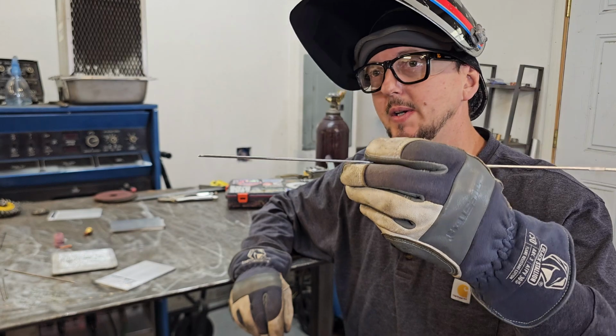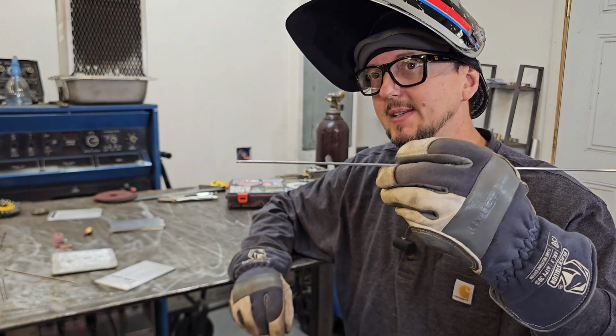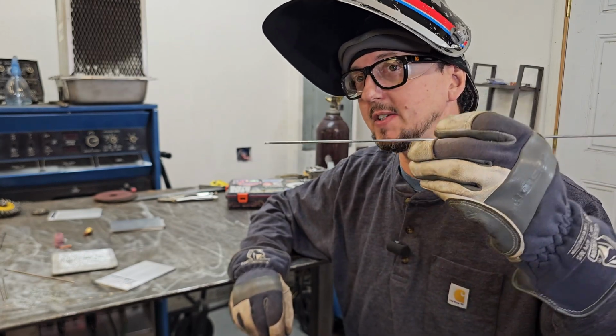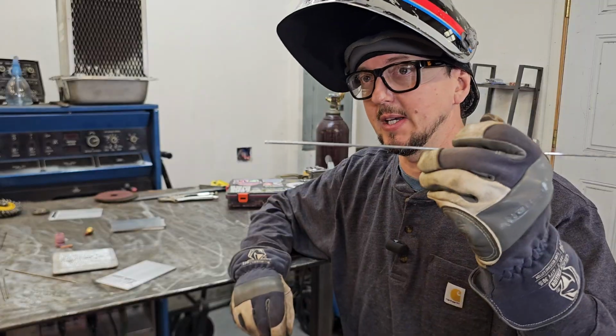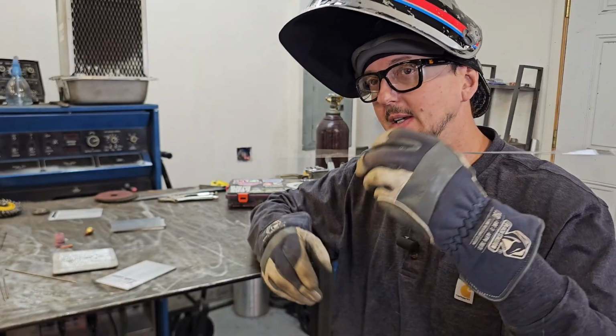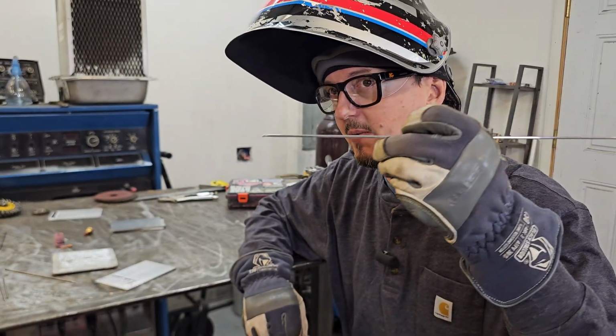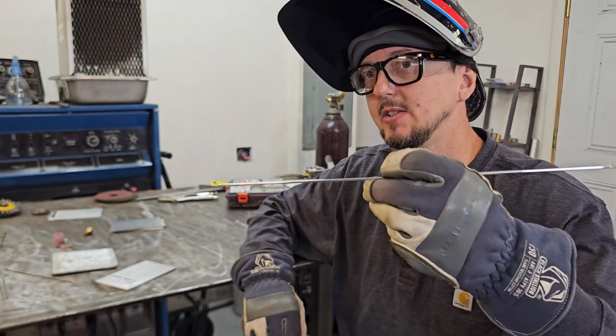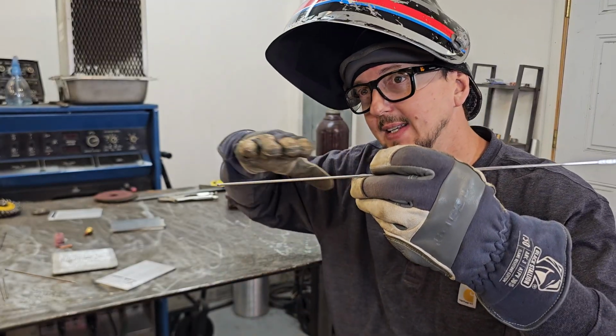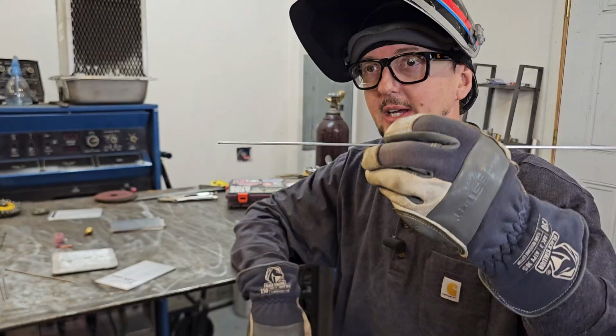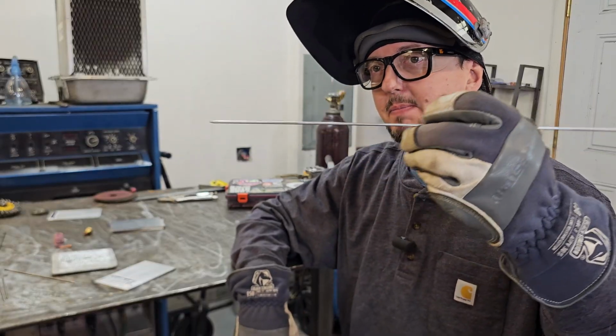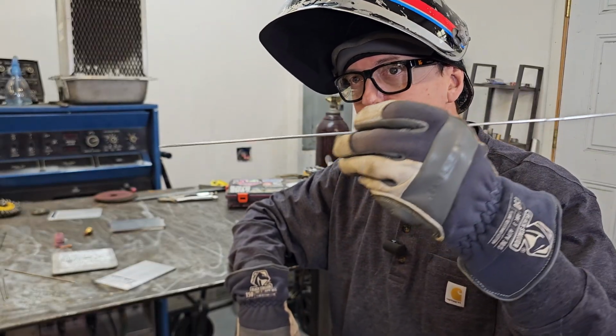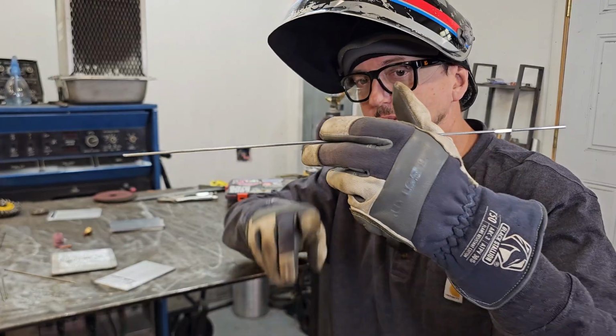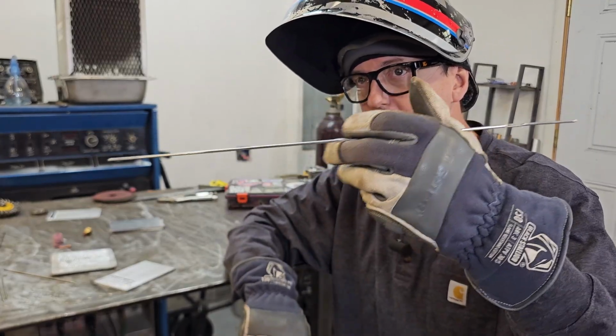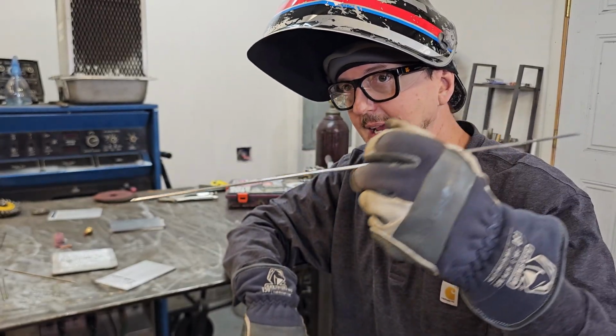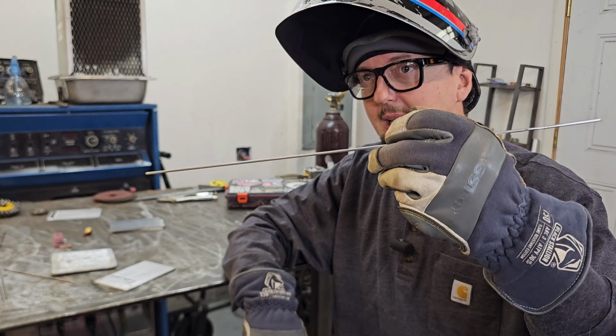And this is really going to develop that, because you're going to be dipping real quick, and you're also going to be going through a lot of filler metal, because each time that you dip, especially with 3/32 like this, you're going to really want to push a little extra into the weld pool so that it doesn't flatten out that bead too much, okay? So each time that I'm dipping, as I dip, I'm also pushing in a little bit, and that's with these front 2 fingers. So I'm pushing that in as I'm dipping in with my hand movement.